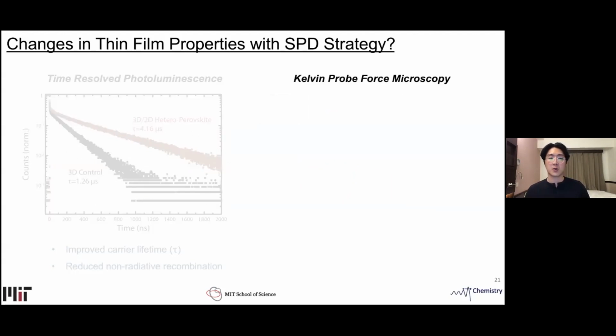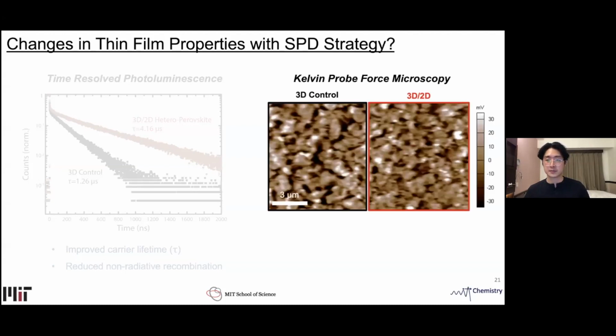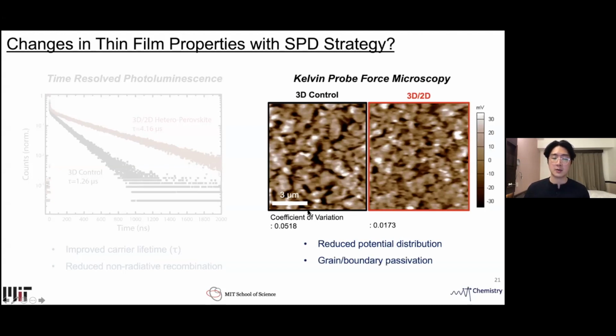We also perform Kelvin probe force microscopy to probe the surface potential of the 3D control and the 2D heterostructure. By analyzing the coefficient of variation, we learned that there is a reduced potential distribution with the 2D heterostructure compared to the 3D control, which we assign to be the result of grain and grain boundary passivation.